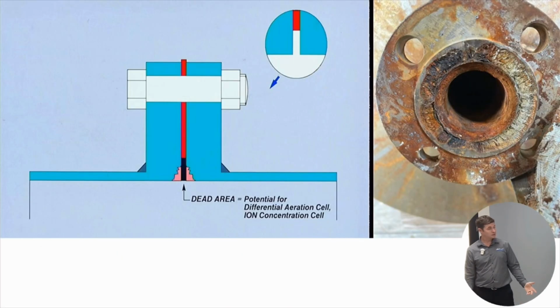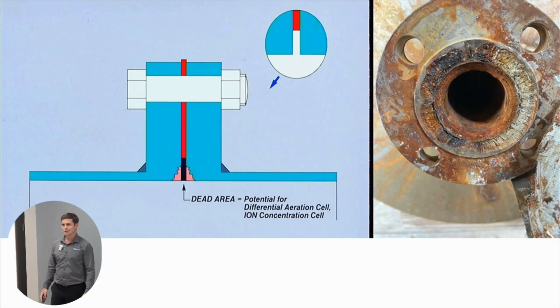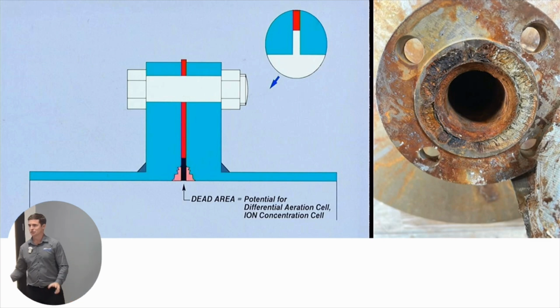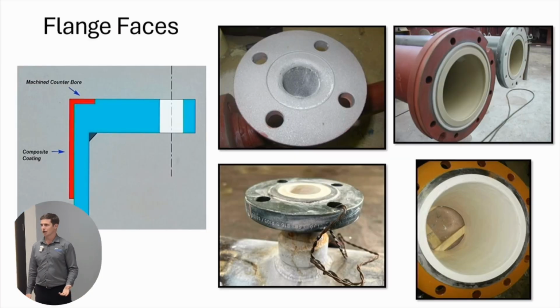Now, do you have any flanges that look like this? Crevice corrosion, it's pretty prevalent. It's the small areas that cause us the biggest problem, it seems like. We deal with that with a spec, I don't know if you've seen it, where we recommend that you rebate the flange down 60 thousandths on the ID. That works great. You fill it with coating. The coatings are fully machinable. You can put it on a lathe if it's possible to machine it, but you don't really have to. We're able to get plus or minus 5 thousandths, which is the BP spec, right here, no problem without machining.